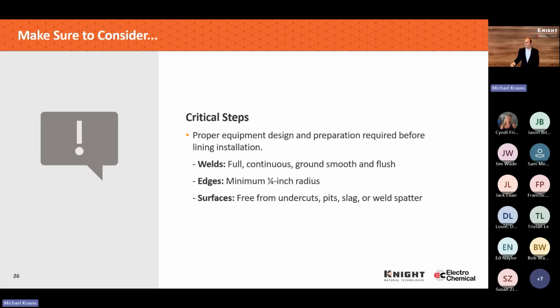And making sure that the metal welds are full and continuous and ground smooth and flush, that there's a good radius on all edges, and that the surfaces are all smooth. There's no undercutting, no weld slag or splatter on there is absolutely critical in order of getting a good lining, getting good adhesion, and getting a successful lining system.